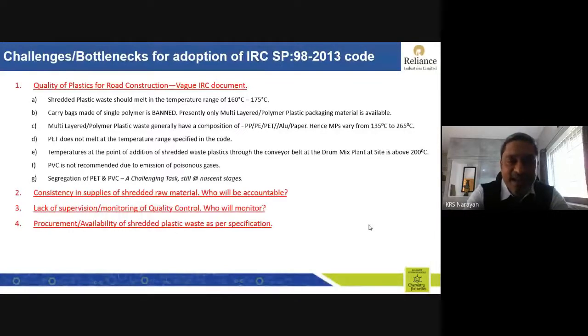Multi-layered polymer plastic generally has a composition of different materials. As I said, it's multi-polymer, then multi-material, that is polypropylene, polyethylene, PET, aluminum, paper, etc. So the melting points vary from 135 to 265 degrees Celsius. PET, which was mentioned as PET bottles that can be used in the 2013 code, does not melt at this temperature. Because, you know, we are one of the largest polymer and petrochemical companies in the world. So we have a very, very strong laboratory which analyzes all types of polymers. And we found that PET was not melting at all.